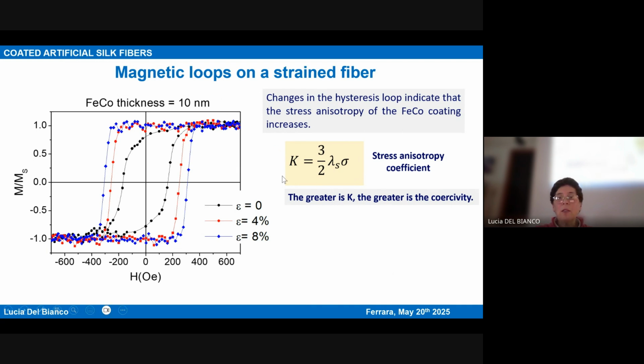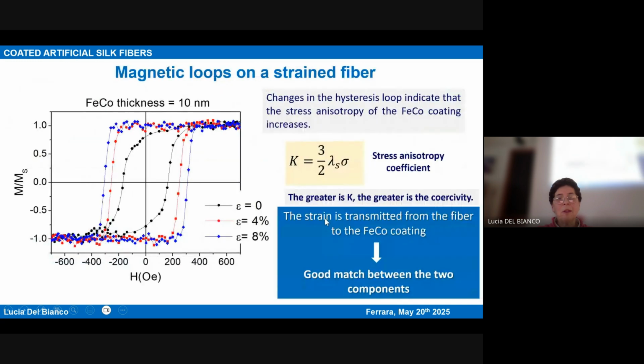You remember the stress anisotropy coefficient is given by this expression, and therefore with increasing stress, you are increasing the anisotropy coefficient. But you should remember that the greater is K, the greater is the coercivity, and therefore you see that the coercivity increases. And this is a very good result because it is a really difficult measurement, and therefore it's great satisfaction to succeed in doing this,